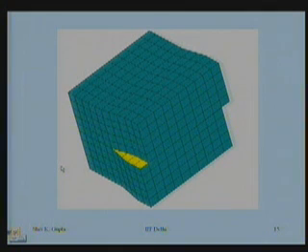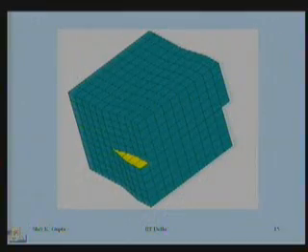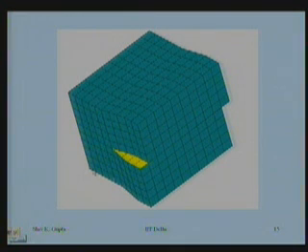If the nature of the bond is very flexible, a very metallic kind of bond, it may go beyond 10 planar spacings. But if partial covalency is present, then it will not go very far off. So these strains do not go away very far, but they are visible around here very much. Now let's see what has happened.